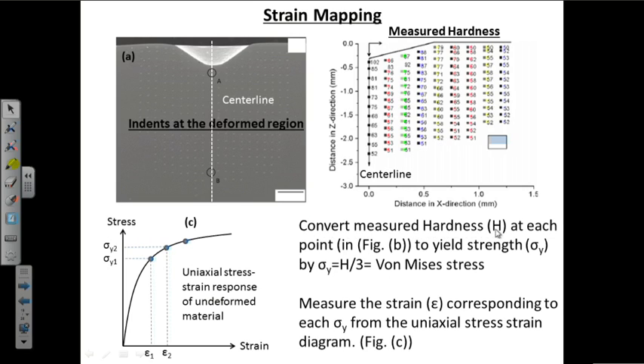In the next step, we convert those hardness values at each point to their corresponding yield strength by using sigma y equals H over 3. These yield strengths are nothing but the von Mises stresses at each point inside the plastically deformed region. Now, if we have the uniaxial stress strain graph of the undeformed material, we can find out the strain induced at every point if we know the yield strength at each point where the indents were measured. So, if I measure an indent at a certain point, we know the sigma y for that indent, and we know the corresponding strain associated with that indent. This is the way we can map the strain distribution beneath the macro indent, and this method is called strain mapping.